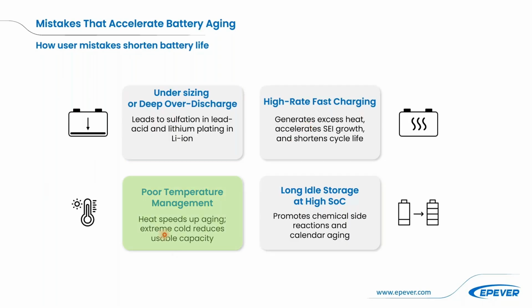And of course, this adds heat and speeds up the SEI growth. Fast charging and discharging also contribute to a shorter lifespan. Then poor temperature management, improper ventilation. We talked about the role of temperature, so that's important. And these are the mistakes. So we put the batteries into a very harsh environment, either very cold or very warm, and still do not change our consumption. We do not adapt it, and then we have a shorter lifespan.